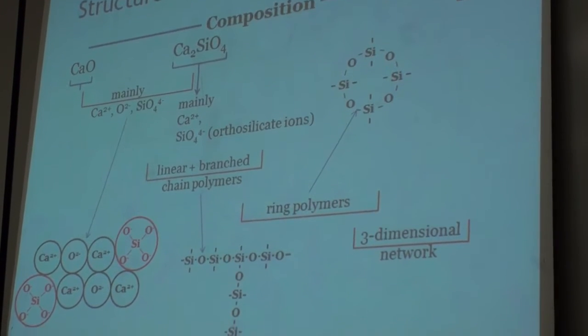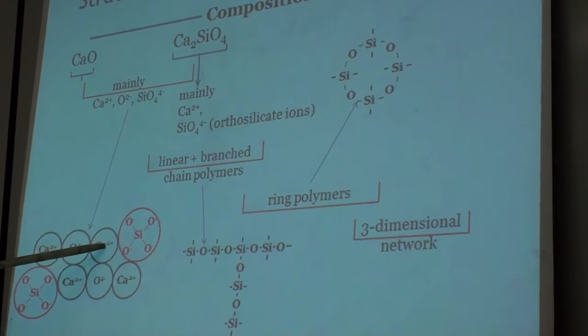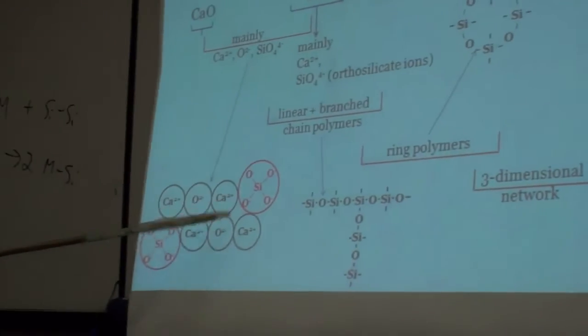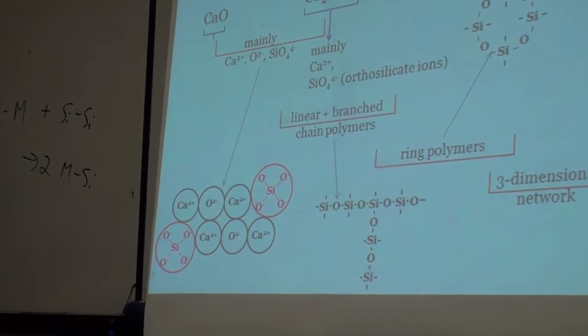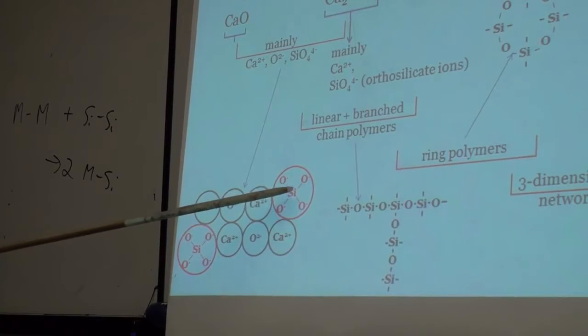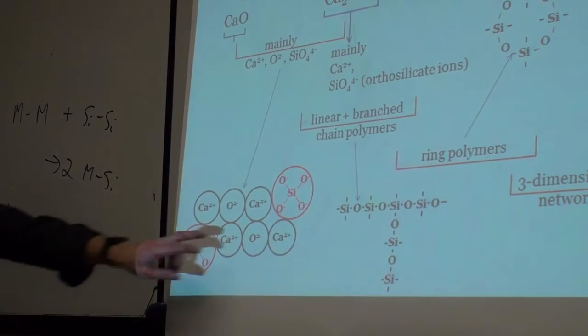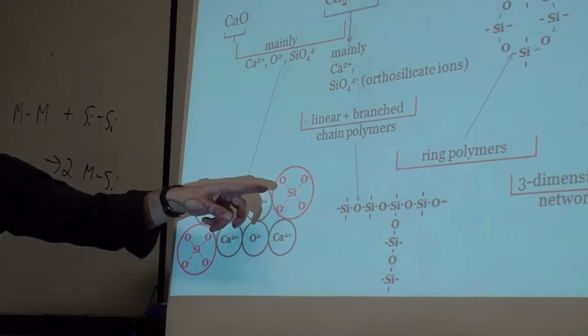as we were talking about earlier with Elmira, your question. You can consider this to be a discrete ion, or you consider that to be a silicon-calcium preferential second nearest neighbor. This thing's going to be surrounded by calciums, and so as long as you don't have very many silicons, that will be a rough model that this thing is equivalent to a complex SiO4 ion.